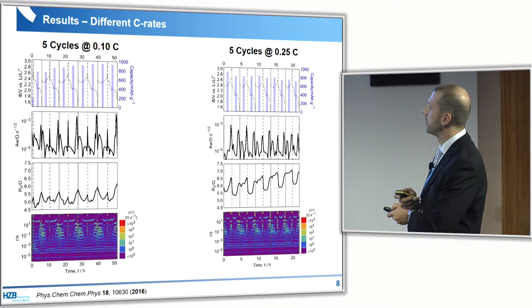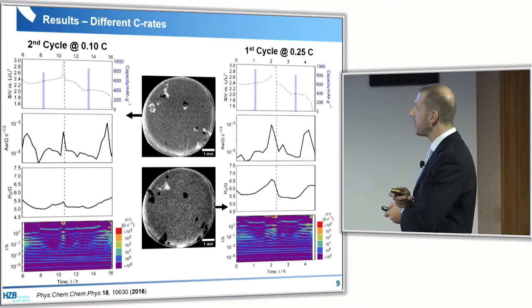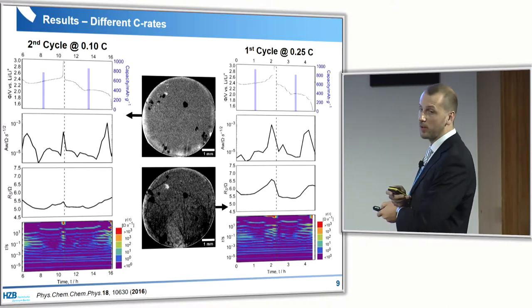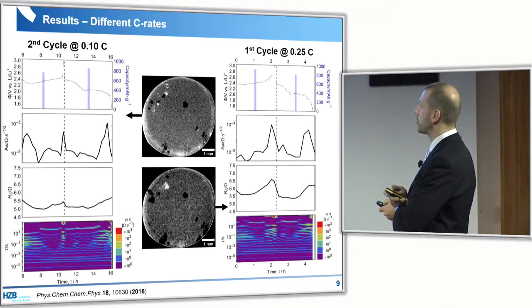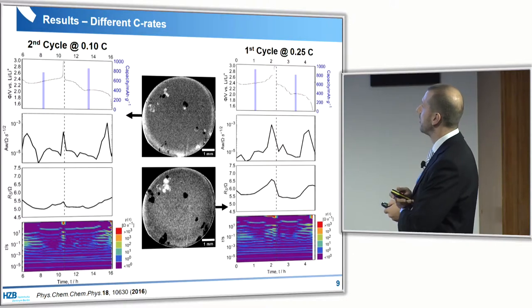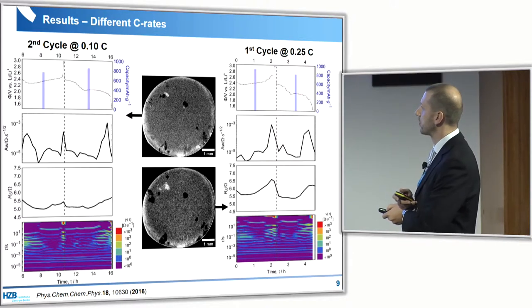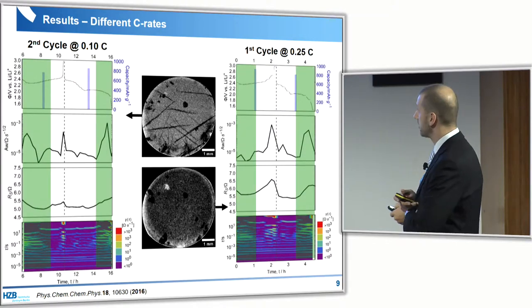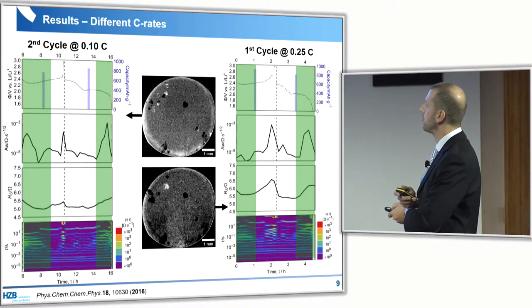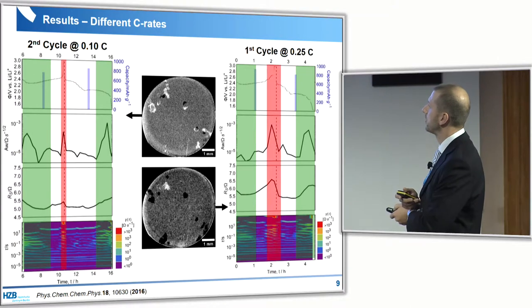Every time there is a dip in the voltage curve, you also see an increase in the resistance, which is known. Zooming into these two cycles, you can again see the very sharp sulfur charge transfer process, which correlates very well with the appearance and disappearance of the chunky lithium dendrites. When you increase the C-rate, this mapping changes: one relaxation process is located to the Li2S formation and solution-precipitation-dissolution process, and the other, much more narrow, corresponds to the sulfur charge transfer process.